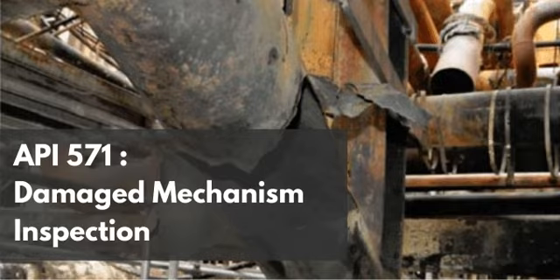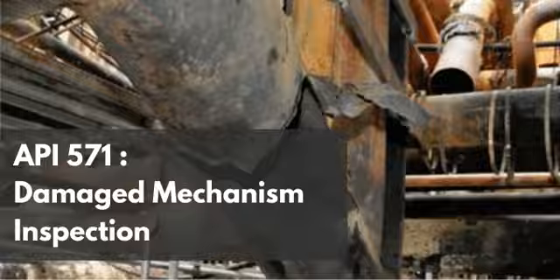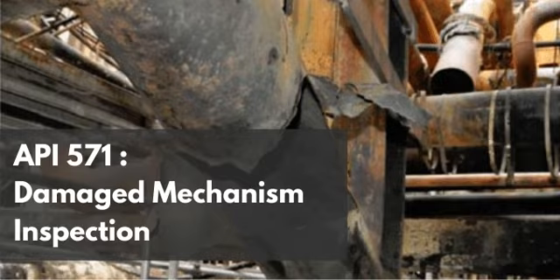So if you're out there managing this unit, you have to understand that your reboiler firing rate isn't just a dial you turn for process efficiency. It is your primary defense mechanism against catastrophic weld thinning. You are the gatekeeper of the thermal degradation threshold. You really are. If you push for just a little more throughput by cranking the reboiler heat, you might look like a hero on the daily production report. But you might just be carving a half-thickness groove into your weld seams that will blow the unit up next year. That is the exact unvarnished operational reality that the metallurgical failure data is trying to convey. You cannot divorce process operations from asset integrity. They are the exact same thing.